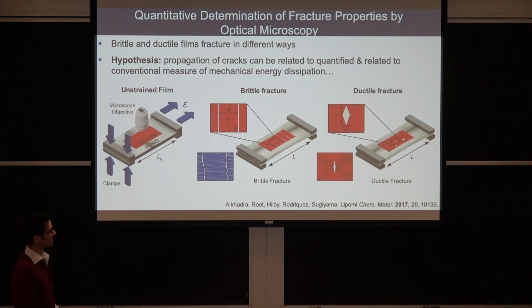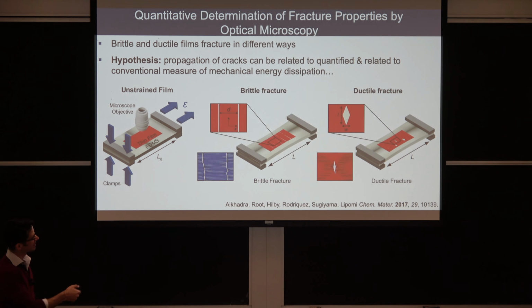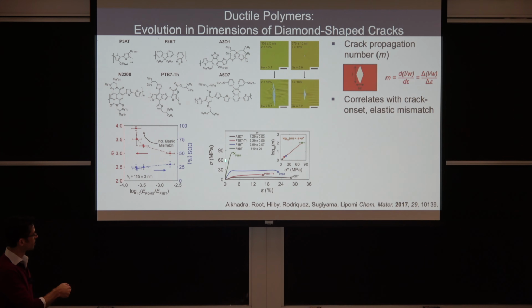Now, it's also possible, I've got to speed up because there's something I want to get to. It's also possible to extract information from the crack shapes. So these ductile films form these diamond-shaped cracks. And this work was done by Mohammad Alkhadra, who was a BSMS student, now a PhD student at MIT, and Kristan Hilby, who's a current undergrad student graduating this year. So it's possible to take the growth rate of these diamond-shaped cracks and correlate them to properties that you would measure by these stress-strain curves.